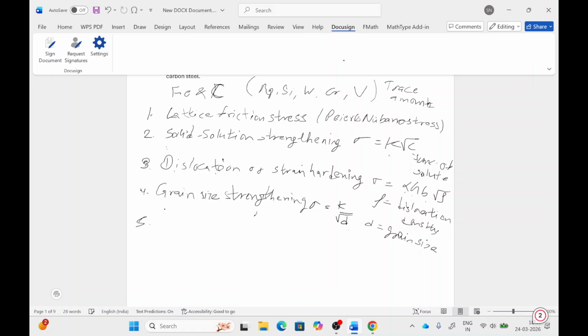Fifth contribution is from precipitation hardening. Precipitation hardening in steel results from the carbides of iron, niobium, titanium, and vanadium. The carbides forming from these elements result in precipitation hardening, or dispersion hardening also.